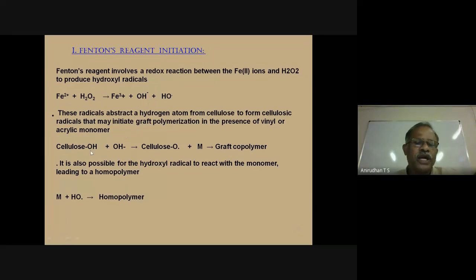They abstract one hydrogen atom from the cellulose, and we have a macro radical, just like cellulose O dot. This macro radical is highly reactive to your monomer. I have already mentioned that you can utilize a wide range of monomers, vinyl monomers or any other monomers: acrylamide, acrylic acid, methacrylic acid, glyceryl methacrylate. Any type of monomer can be grafted onto this cellulose.